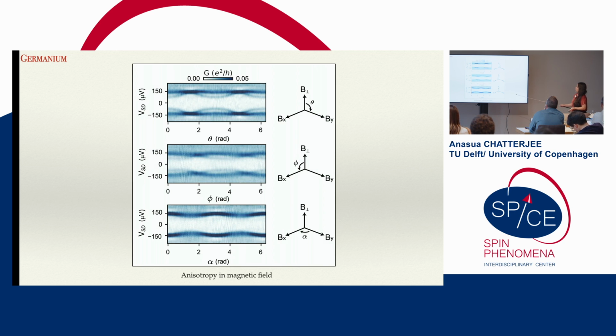We also see an anisotropy in magnetic field, and this is something that's expected for germanium. It's seen also in germanium quantum dots and for spin qubits, but it's maybe not so expected in this kind of hybrid superconductor where the superconductor has kind of renormalized the G factor. And so this was also a bit surprising to us, but yeah, we have to explore it further.